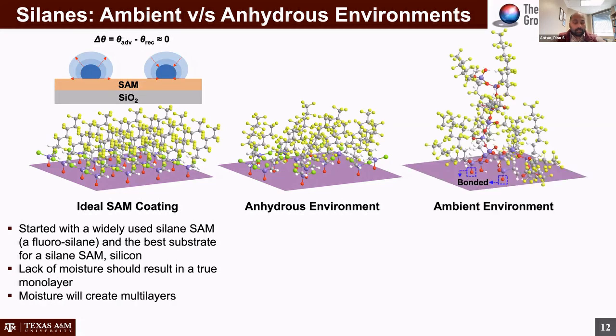And finally, in a real environment, or rather an uncontrolled real environment, where you can have water vapor present in the air, water dissolved in the solvent, etc., you will tend to form multi-layers on the surface. You hydrolyze the silane molecules before they even get to the substrate, and they tend to bond with each other. And so you have multi-layers on the surface, which is what I think a lot of us see in the literature in the thermal transport area.